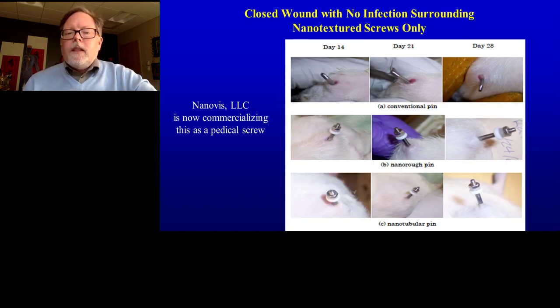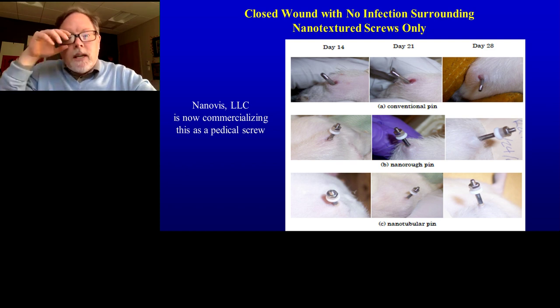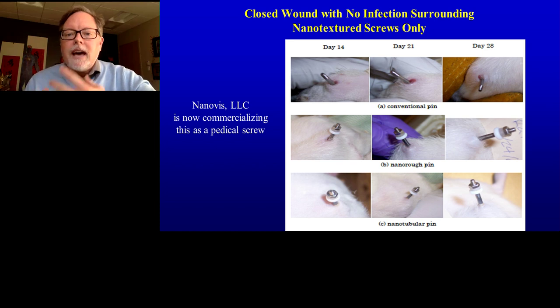When we look at the wound, the exit wound, where the metal is coming out of the rat, again, the spot that the prosthetic would fit on, it's clear to see why the nano-structured implant did so much better. This first row of images is the pin that's used today. You can see an open wound. After 14 days, 21 days, 28 days, that red tissue that you see is inflamed tissue. It got infected. There were signs of bacteria on the screw crawling into the femur into the rat. So it was a clear problem when not having nanoscale features.